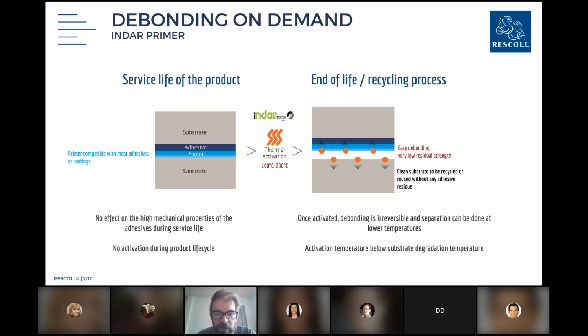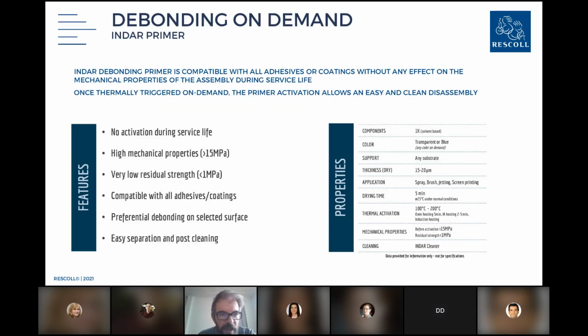What we offer is an irreversible debonding. It means that after heating, you cannot reuse the part because it is completely weakened. It's a one shot. The features of the primer: no activation during service life, and very high mechanical properties when we consider bonding. We are over 15 MPa, which is very high, before triggering. After triggering, the residual strength is very, very low, below 1 MPa.